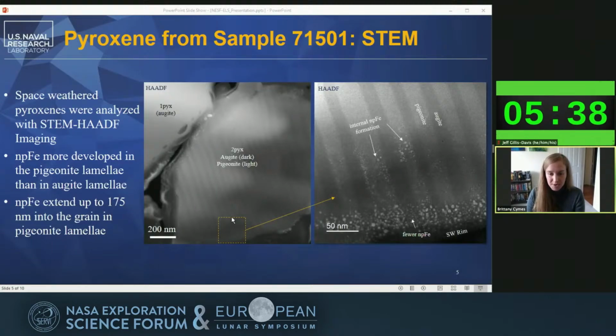And upon close inspection of the space-weathered rim of the exsolved grain, you can see that fewer nanophase iron particles form in the augite lamellae than in the pigeonite lamellae. In addition, we see nanophase iron particles forming up to 175 nanometers deep into the grain interior of the pigeonite lamellae. We don't seem to see this trend in the adjacent unexsolved augite. It develops nanophase iron particles on the same order as the pigeonite lamellae, and we thought, maybe it's a difference in the iron content that could be behind this textural difference we see in the exsolved grain.